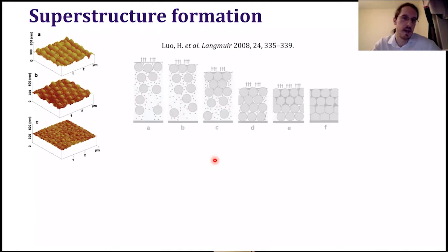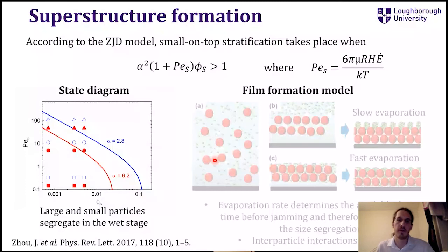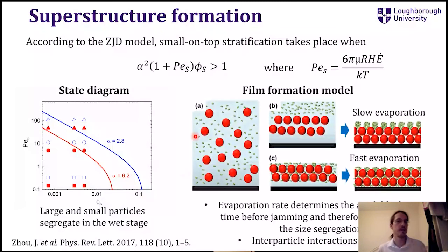We came up with a model for how these structures form, which I'm going to pass over a bit. I'm just going to go to how we explain it finally, which is this film formation model. So basically we ended up explaining it by saying, well, we have a size segregation, like I was saying before. We have this kind of stratification between large and small particles, and this is what happens for all evaporation rates.